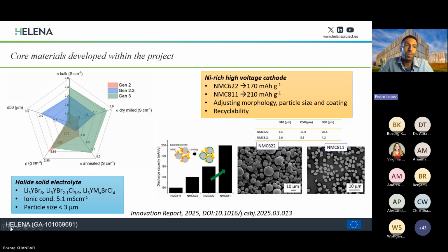Yes. So in terms of materials that have been developed within the project, this is an innovative project which relies on a new halide solid electrolyte material. This electrolyte is the core of the technology in this regard. Several generations of solid electrolytes have been developed based on lithium, yttrium, bromide, and chloride, and some dopants. We've been targeting several requirements for the solid electrolyte, with ionic conductivity as one of the main targets, that we've been able to optimize up to 5 millisiemens per centimeter.